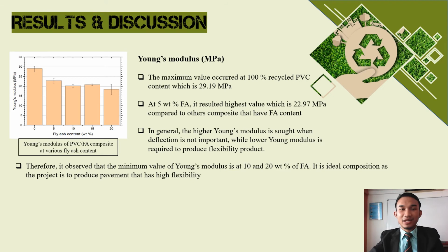In this part, I will share the result and discussion from the tensile test. The first mechanical property is Young's modulus. From the graph, we can observe that the maximum value occurred at 100% recycled PVC content, which is 29.19 megapascal. At 5 weight percentage of fly ash, it results in the highest value, which is 22.97 megapascal, compared to the other composites that have fly ash content.